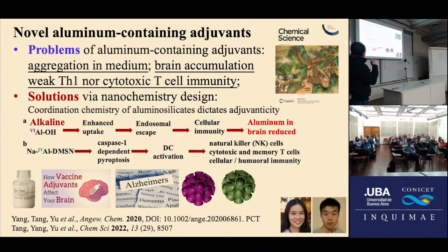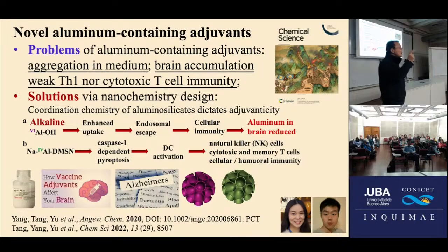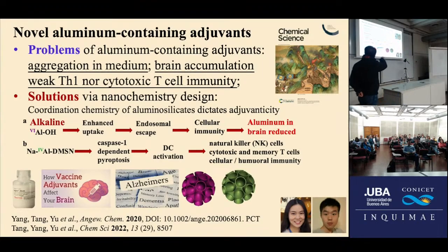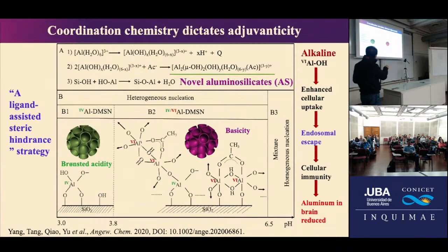And we can also do some interesting fundamental chemistry here. We know aluminum silicates are the major composition of zeolite. Here, we use this concept in the design of aluminum silica nanoparticles, where we can control the coordination chemistry of the aluminum, either 6-coordinate or 4-coordinate. These two adjuvants have very different adjuvancity. For example, here we could introduce binuclear 6-coordinate aluminum onto the silica surface.